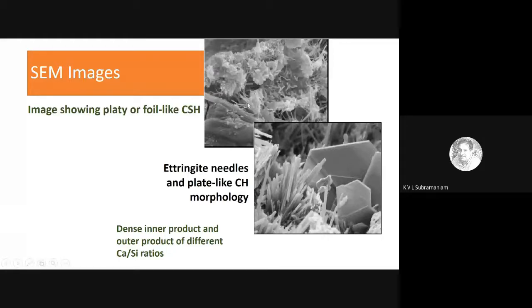You can see that it looks like several plates that have been loosely assembled. You can see the gaps between the plates, which is where the water resides. And to give you an idea of scale, the gap that you see here between the plates will be on the order of fractions of microns. If I zoom further, I may see these needle-like structures, which are basically the calcium aluminate or sulfoaluminates that have formed in the system, which we call ettringite, and also calcium hydroxide, which is one of the byproducts of the hydration reaction, forms these hexagonal crystals, because calcium hydroxide is a crystalline material.